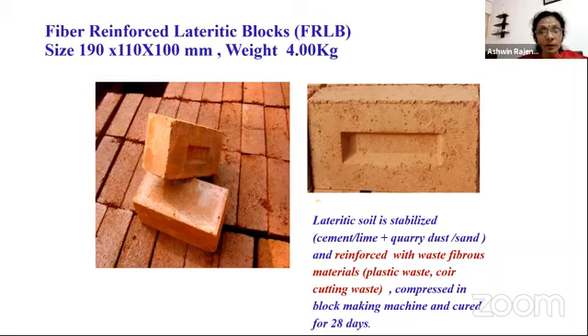But in the case of the Lato block developed by SERC, they were mixing the lateritic soil with cement or lime based on the property, based on the clay content of the soil. Either cement or lime is decided, and that is used as a stabilizer. If clay content is more, we can go for the lime. So naturally available soil is collected. After checking the gradation of the soil, percentage of clay, sand, silt, deciding about the stabilization material, either cement or lime. I'm talking about the Lato block.